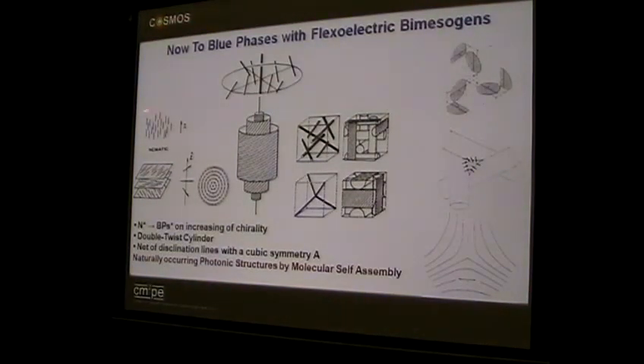So you're used to nematics now, twist them up in 1D and you've got a chiral nematic, the director precesses around. If you get to the so-called blue phases, there are three primary blue phases, there are other subphases. What you see is, first of all, BP3 as you come down in temperature, which is the so-called fog phase, a gray sort of texture. And there are various theories about this.